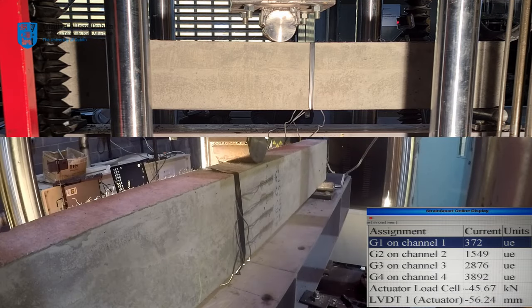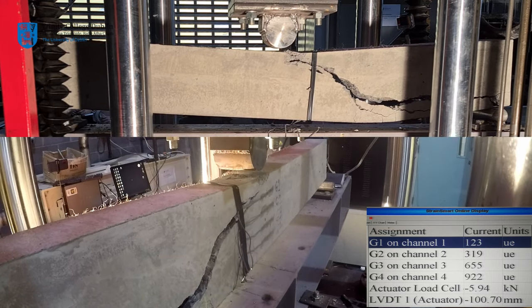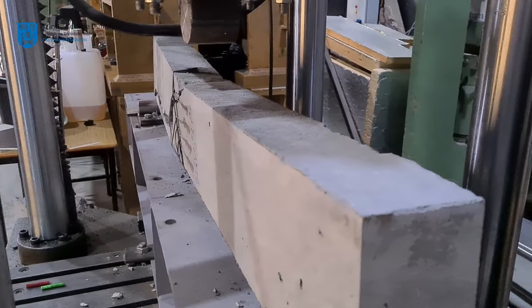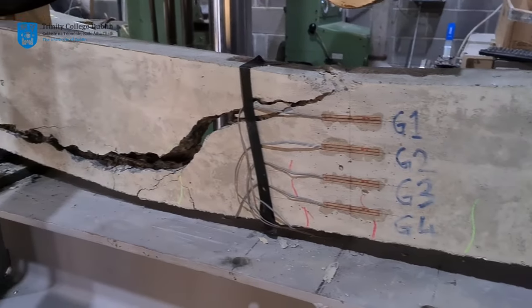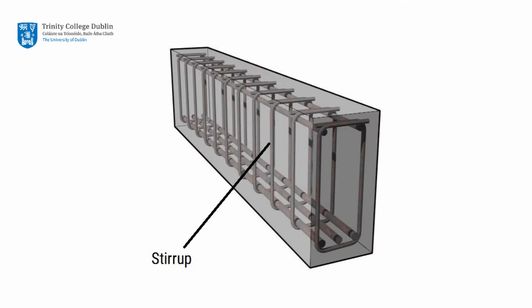With this particular beam, we will observe that shear failure takes place. A crack opens up between the support and the loading ramp, partially following the length of the reinforcing bar. This is a force control test. As such, the actuator attempts to apply the next force increment, but due to the compromised condition of the concrete, the beam fails suddenly as the crack widens. The observed shear failure in this experiment is due to the lack of shear reinforcement in the beam. The use of shear links, also known as stirrups within the structure, would have increased the shear capacity and led to failure in flexure.